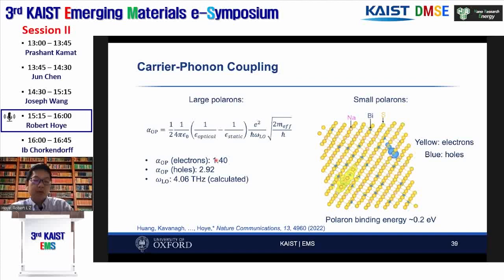And we know that there's no carrier localization in the perovskites. So this is probably not what's causing the carrier localization. We're next to look into the small polarons. What we did here was we investigated this computationally. We introduced either an electron or a hole and then relaxed the lattice to see where the electron or hole went to.